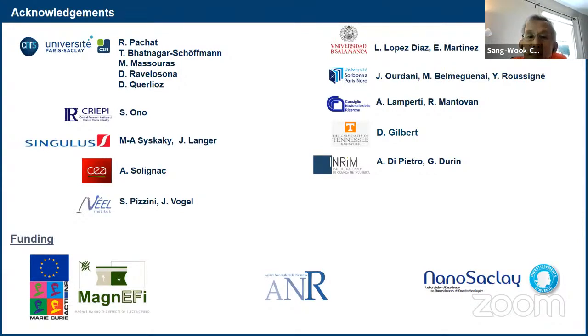Thank you. Okay, well, to your first question about ion mobility in hafnium oxide, it is true that there is a lot to be done. Actually, I'm starting to connect more and more with the memristor community because they know all about this. And indeed, doping of hafnium oxide may be a very interesting avenue to increase mobility. But also another important thing is the counter electrode. I didn't say much about this, but we're using ITO as a counter electrode. So I think that probably the ITO is also contributing to the oxygen transport in the hafnium oxide.